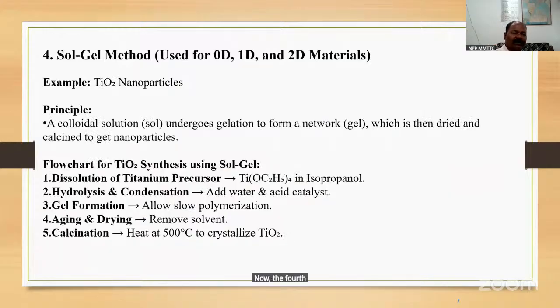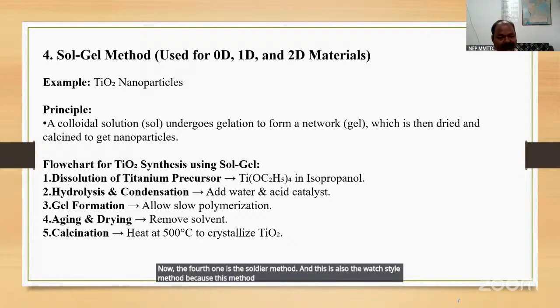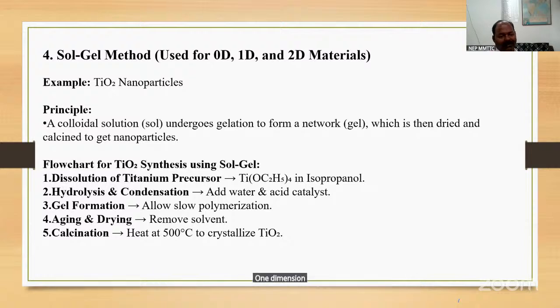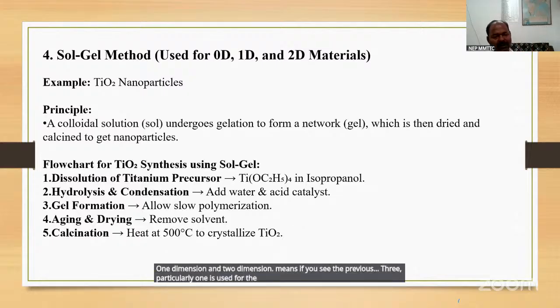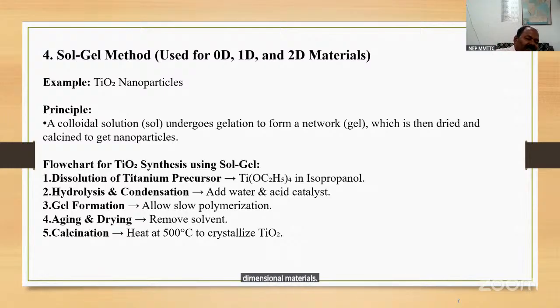Now the fourth one is the Sol-Gel method. This is also a versatile method because it is used for 0 dimension, 1 dimension and 2 dimension. If you see the previous three, one is used for 0 and 1, another for 1 and 2, and the third also for 1 and 2, but this is for 0, 1 and 2 dimensional materials. An example is titanium oxide nanoparticles. The principle of this method is that a colloidal solution undergoes gelation to form a network gel, which is then dried and calcined to get nanoparticles.